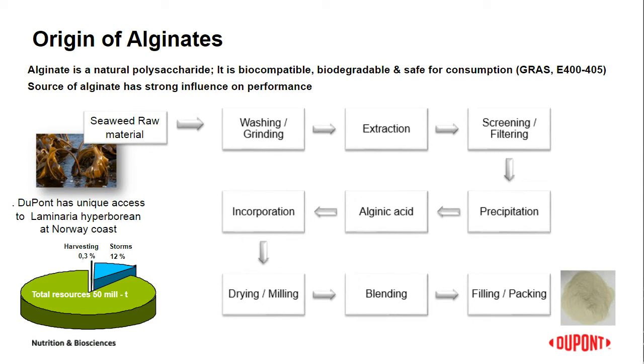Now the alginate is in solution and must be recovered in a solid form. Evaporation is not practical because these solutions are too dilute. Therefore, calcium salts are added again, which precipitates the alginate in the form of fibers, which are then separated on screens and washed with water. The calcium alginate fibers are afterwards converted to alginic acid in an aqueous-based ion exchange process. From here, the product is converted to the desired salt form, and for anti-reflux formulations, the sodium derivative is a common one, but all other forms like magnesium are also available.